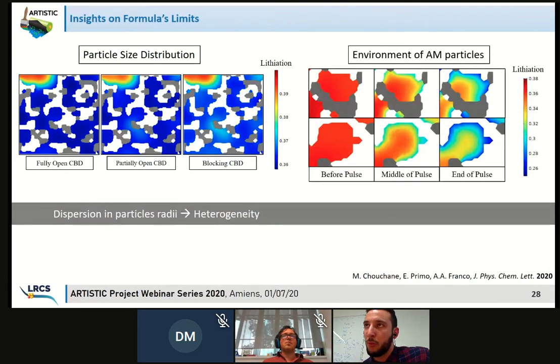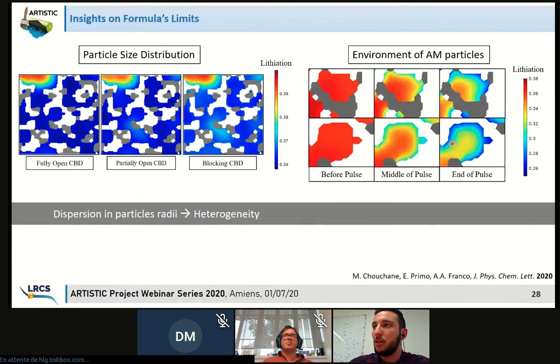Moreover, the environment of the active material particle plays also a huge role. For instance, once again, the CBD morphology. Here there are several snapshots of two different particles at different times of the pulse: before, in the middle, and at the end. So here you see before the pulse, as we said earlier, the concentration is homogeneous, so it's nice. At the middle, you have a gradient forming, and at the end, it equilibrates more or less.